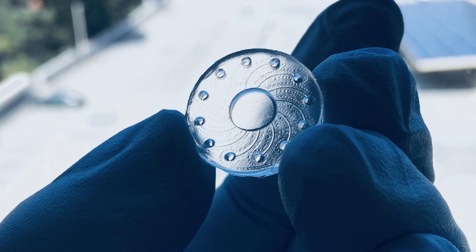Once the successful prototype was completed, it was extensively tested for its performance in channeling and collecting fluids. Flow rates of artificial tears in the channels were measured at different levels of hydration, with zero flow measured at complete dehydration and full spontaneous flow observed at full hydration. A noteworthy observation was that when the hydrogel was mildly dehydrated, liquid flow in the channels would stop, but when additional rhythmic pressure was applied, the flow would resume.